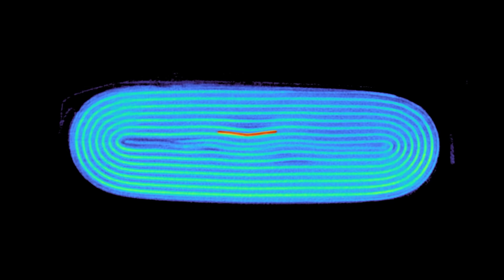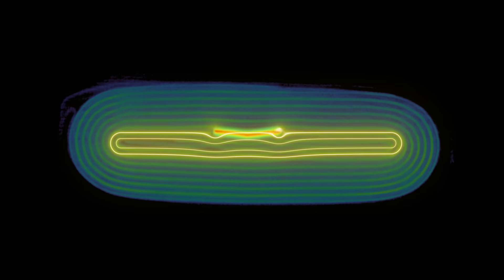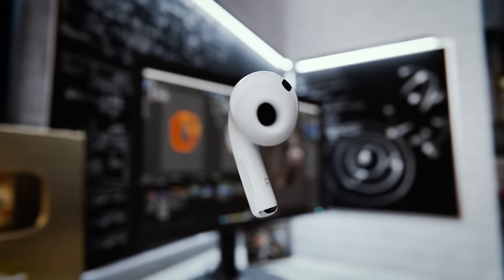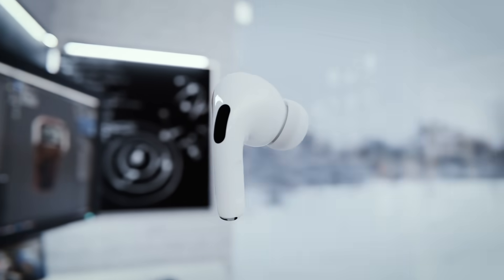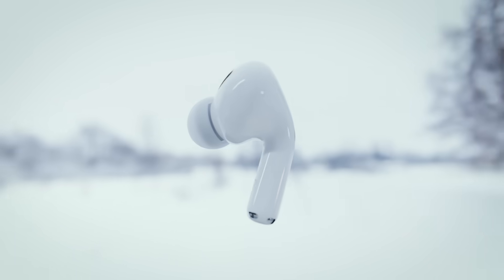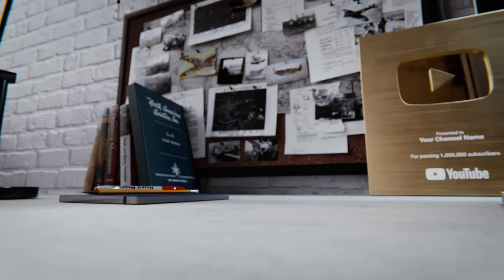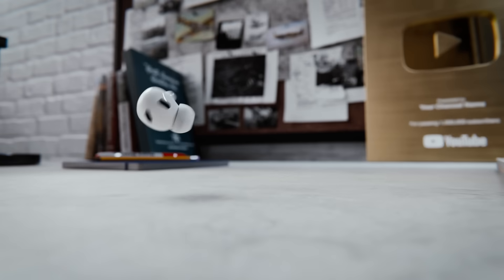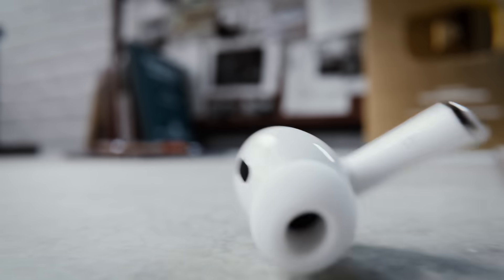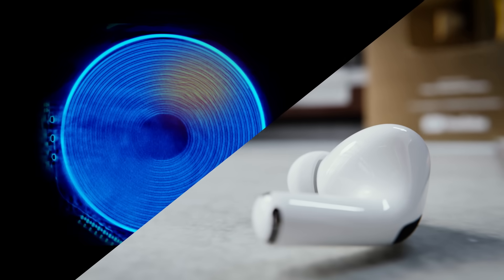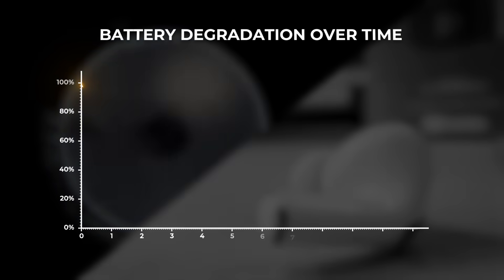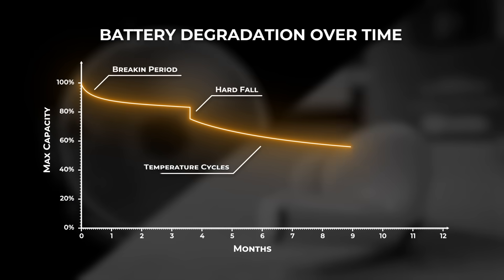Here in the scan of the charging case, there is a faded patch in the corner. That is where the electrolyte has broken down. It's no longer making contact with the electrodes. So ions cannot move through that region. This is literally a dead zone in the battery. These zones can form when you move your AirPods from a warm room to the cold outdoors, or if you accidentally drop them on the pavement. These sudden changes in temperature or physical shocks can stress the battery's internal layers and start breaking them down. And it's one of the reasons your AirPods might start out with 6 hours of battery life, but after a year the battery life decreases to only 2 or 3.